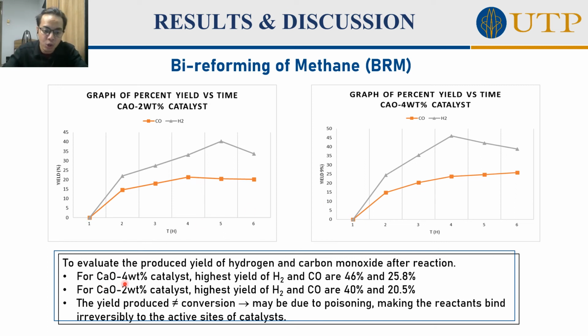And for the CaO 4% catalyst, the highest yield of H2 is 46% here. And CO is 25.8%, which is at the end of the reaction, at the 6 hours. And for the CaO 2% catalyst, the highest yield of H2 is 40% at the 5th hour here. And the CO is 20.5%, which is at the 4th hour.